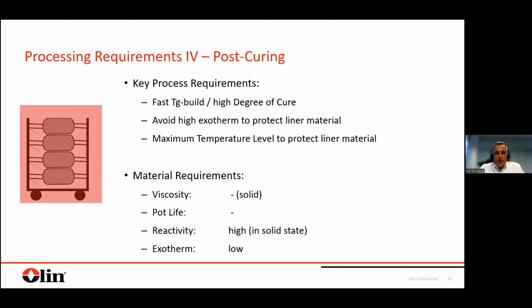The final process step is the so-called post-curing, building the final degree of cure, achieving the final Tg and also the final mechanical properties. Ideally, you want to have this step as short as possible. This determines your cycle time in manufacturing a lot, but still you need to make sure that you protect your liner material. So overall, the requirements in this step are a bit limited. You don't care about viscosity anymore. You don't care about pot life anymore. You're just interested in a high reactivity at a manageable exotherm level.